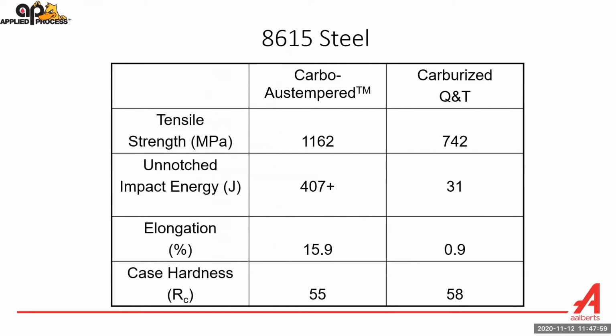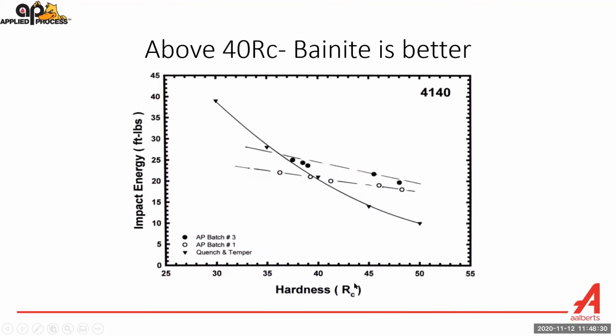We can also do Carbo-Austempering of steels, which we'll talk about in a little bit, and a similar thing happens. When you add carbon, you can improve the hardenability of the material and the hardness, and you can get to extremely high mechanical properties in comparison to oil quenched and tempered carburized steel. This just shows you the tensile strength improvement. The unnotched Charpy increases by over a factor of 10. The elongation increases at essentially the same hardness. There is a limitation. We're talking about 40 Rockwell C or above, so fairly high hardness. That is when bainitic steels are better than martensitic steels.